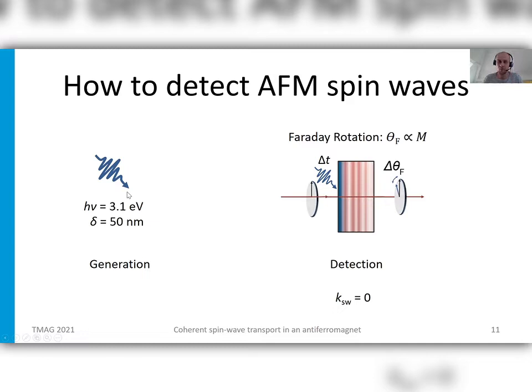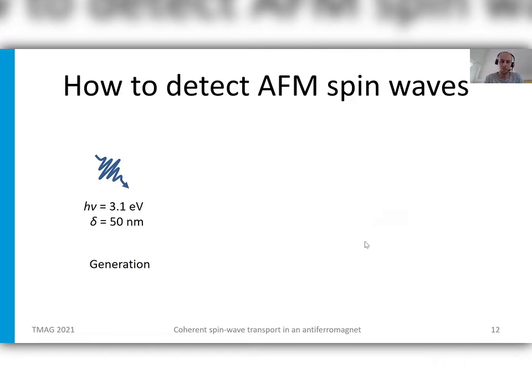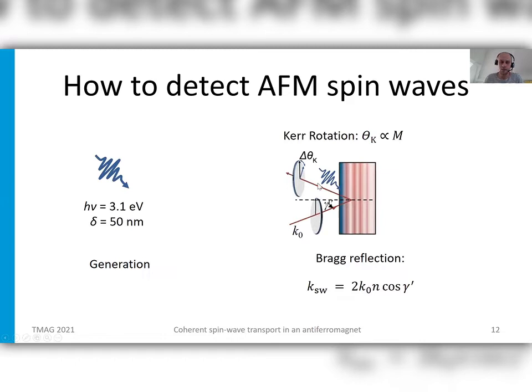There are several ways to detect antiferromagnetic spin waves. The idea is the following: we excite the sample with these ultra short pulses of light with strong absorption, and then we can use below band gap pulses which are partly transmitted through the sample. The rotation of the polarization plane of these pulses is proportional to a net magnetic component, and this is the detection geometry traditionally used for zero wave number uniform spin precession.